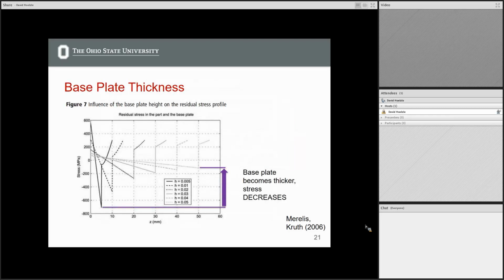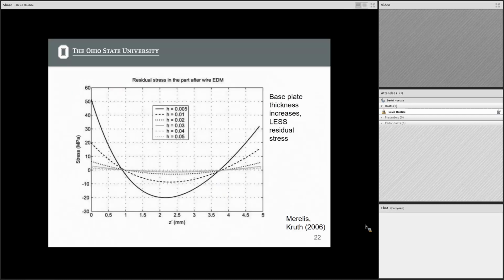So then this was something that I found very surprising. Varying the base plate thickness has a really big effect on the residual stress of the part itself. So by increasing your build plate thickness, you're actually able to really decrease those residual stresses that are going to be built up in the base plate itself. And eventually, when you remove that part, you're going to get a really big reduction in residual stress of the removed part if you make the base plate just thicker and more stiff. So that is a tunable parameter for someone designing an AM system to make a thick enough base plate to really reduce these residual stresses for these parts that are supposed to be immediately implemented after they're printed.